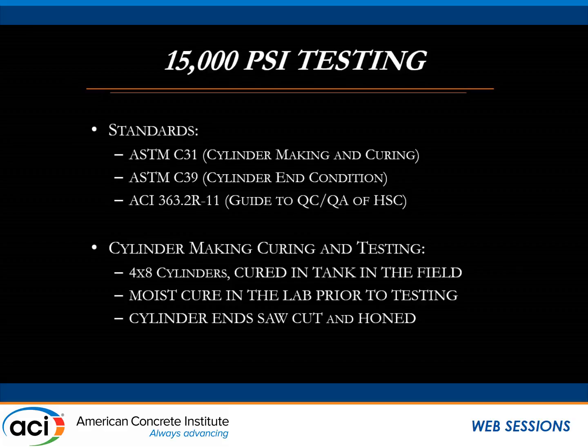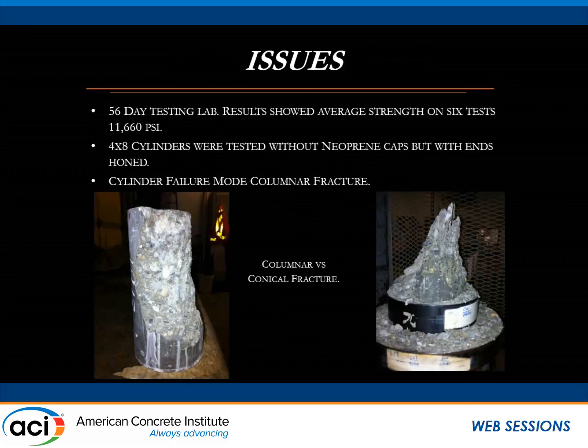So what happened on this job: the first batch of cylinders for the 15,000 mix were tested, and the way it was done, they formed 4x8 cylinders on site, submerged them in a tank, and I think in the next day or a couple of days, they moved them in a truck to the lab and put them in a steam room, a more secure environment. Then they saw cut or ground the cylinders like ASTM C39 tells you to do, and they didn't cap them per the standards. So this whole thing got flagged when at 56 days, we got about 11,660 PSI on the breaks.